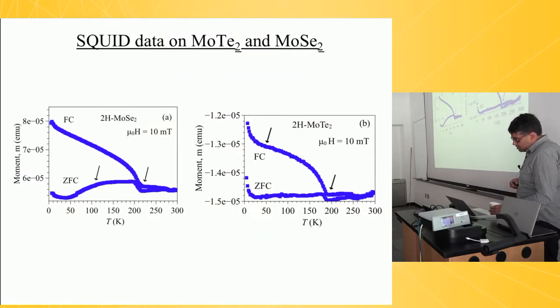So some of you may not believe μSR because many people don't understand μSR, so they're very suspicious of things that they don't understand. So you can put it in a SQUID, which now everybody has one in their lab. And you can measure just the magnetization in the SQUID. So this is zero field cooled. That is, you cool the sample in zero field and then measure the data while warming up. And this is field cooled in 10 millitesla field and measured while warming up.